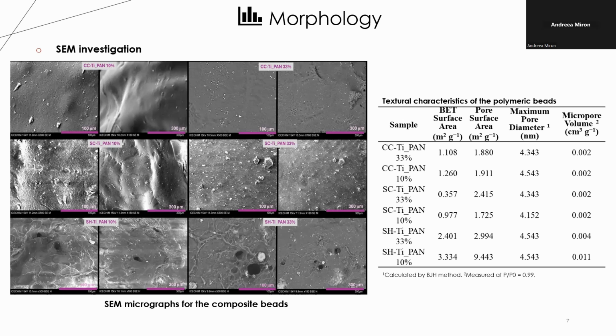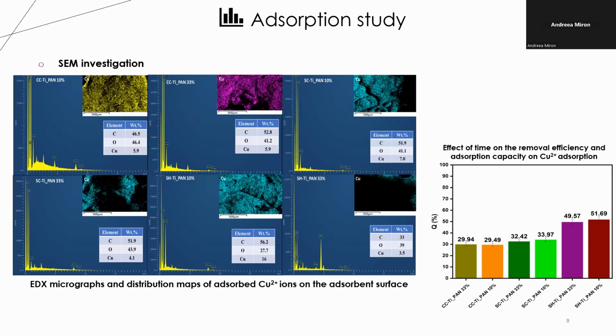in the case of SH series display the presence of large pores on the surface of the beads. It can also be observed that the removal efficiency depends on the type of chitosan used and the percentage of the inorganic organic composite present in the structure of the polymeric beads.